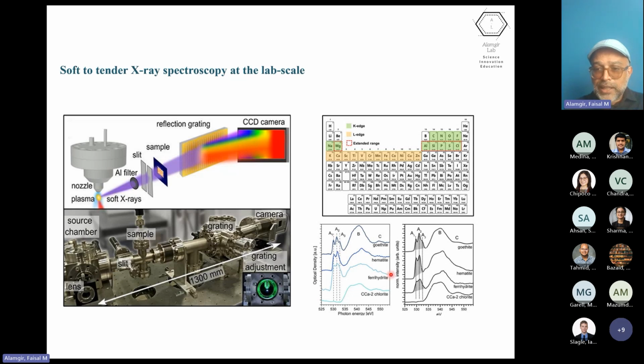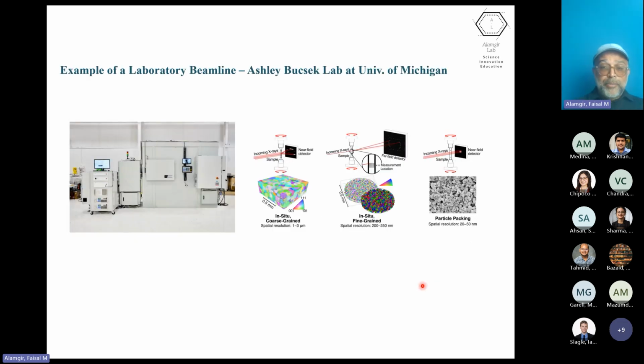So here's a side-by-side comparison of beamline data and the lab acquired data using this type of instrument, and you can see that they're very comparable. The one on the left is the lab acquired one. You can see it's slightly noisier than the beamline one, but if you're interested in the features that you're going to be used for an analysis, the features match very well with beamline data.